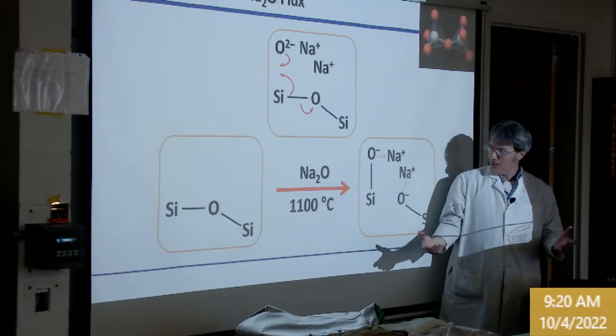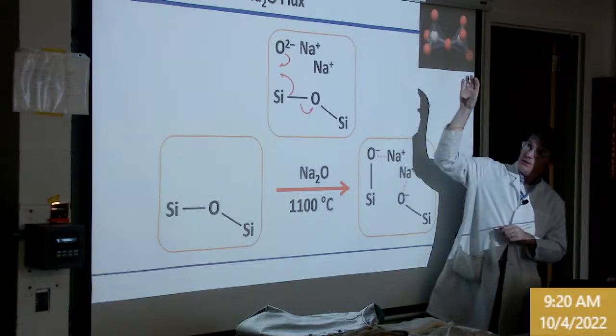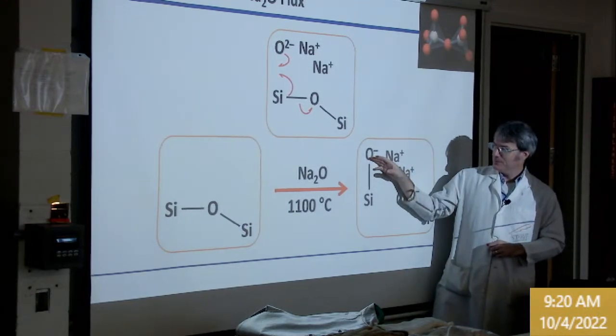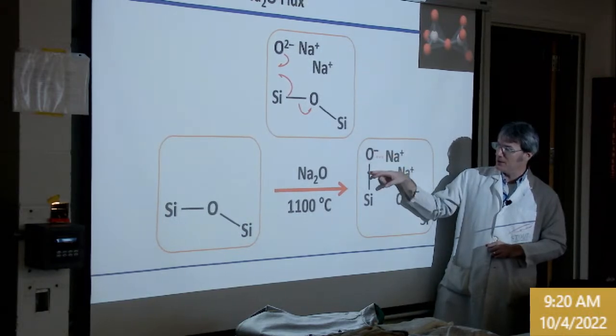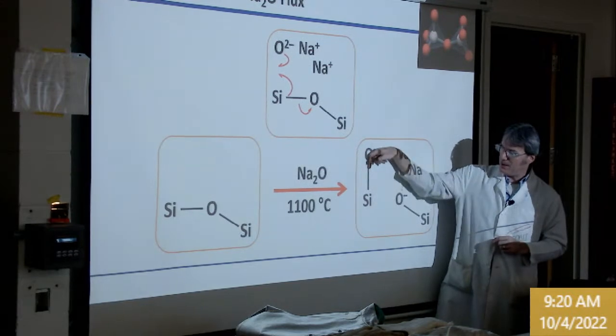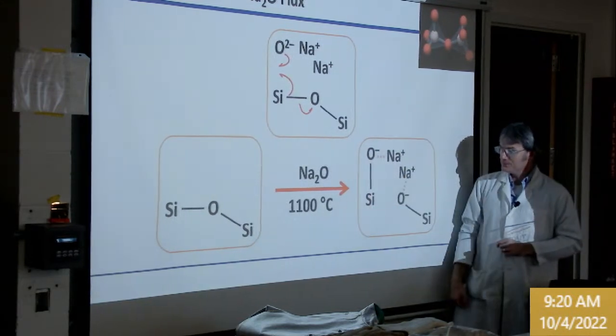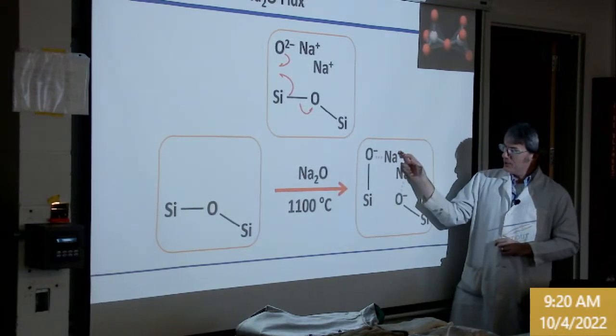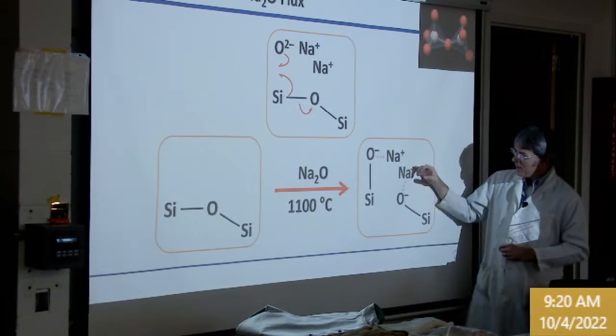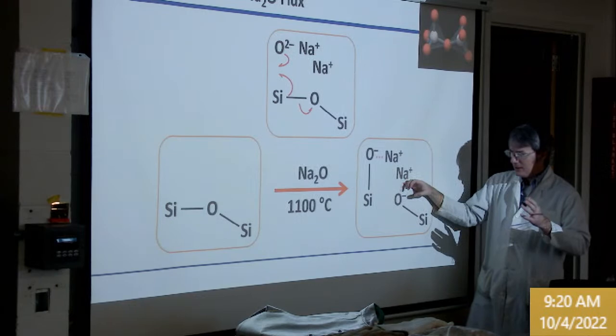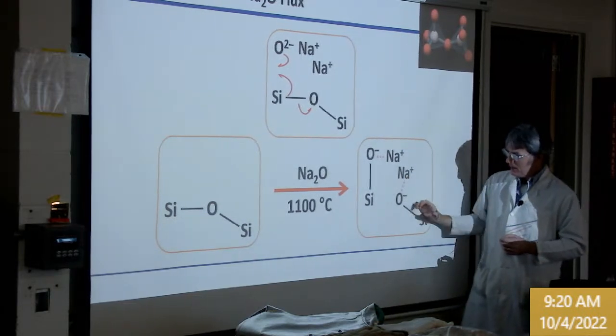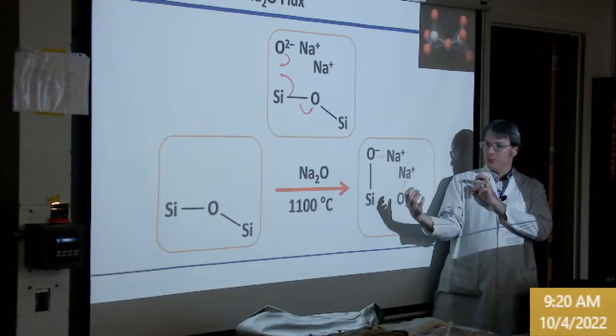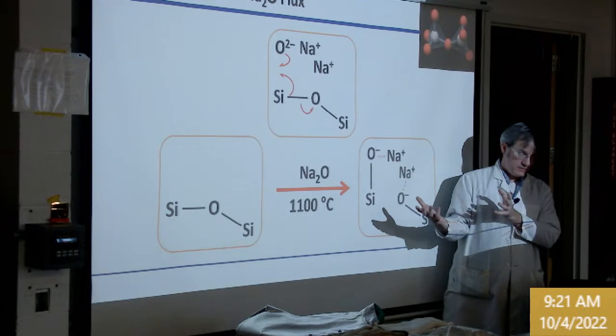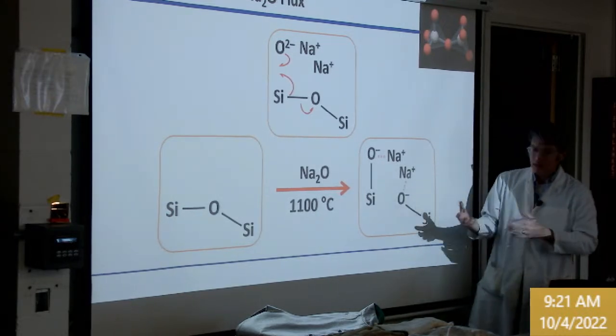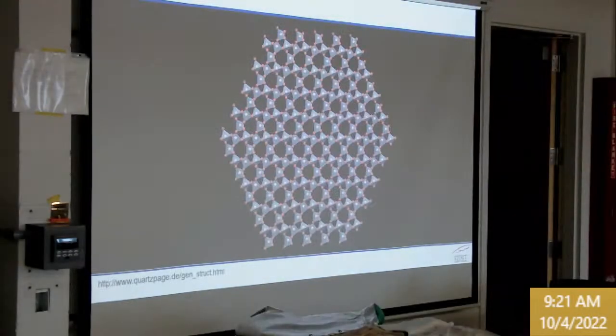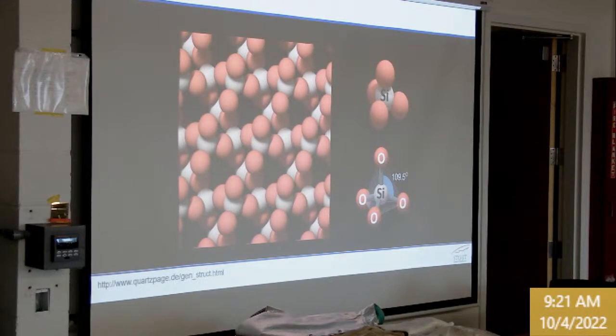You see what happened? So this is now called a pendant, dangling oxide. And so this is a unique case where it has a -1 charge because this charge is now bonded polar covalently to the silicon. And so now we've got one of the sodiums bonded to this oxygen, and the other sodium, not bonded, well, ionically bonded, ionically associated with this oxygen. And you see we effectively snipped this bond and now interposed two sodiums. You follow what's happening here? We're busting up the covalent linkages that previously existed between every silicon, oxygen, silicon, oxygen, silicon, oxygen.